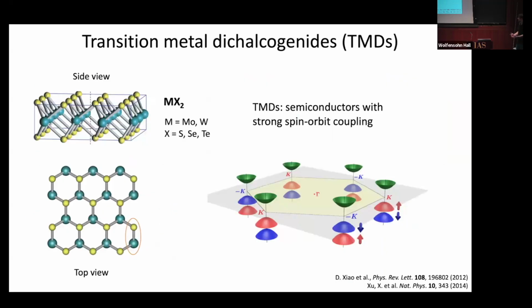Okay, so transition metal dichalcogenides look like this. They consist of a metal atom, some transition metal, usually molybdenum or tungsten, and chalcogen atoms, that is sulfur, selenium, or tellurium. And they're arranged in this particular structure here that has the metal atoms sandwiched by chalcogen atoms above and below. And if you look at the top view image, they form a honeycomb lattice where the metal atoms sit on one sublattice of this honeycomb, and the chalcogen atoms sit on top of one another, when looking vertically, at the other sublattice. And what this does is there is some sublattice symmetry breaking, so you get a very large band gap between the conduction and valence bands. So these are semiconducting materials.